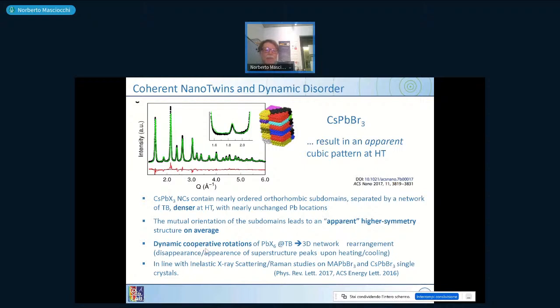So you have dynamic rotation of the octahedra, which changes locally the structure and makes this separation higher, and you have an entropy contribution. This was in line with inelastic neutron scattering and Raman studies of similar compounds which appeared in 2016 and which were not yet understood.